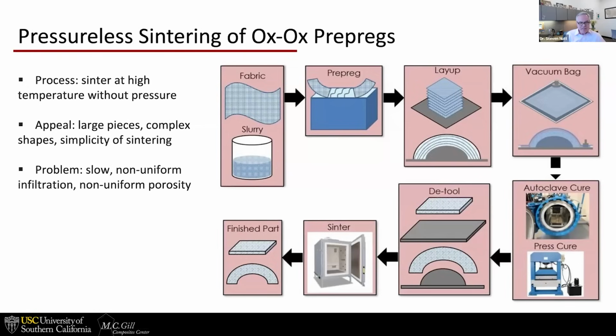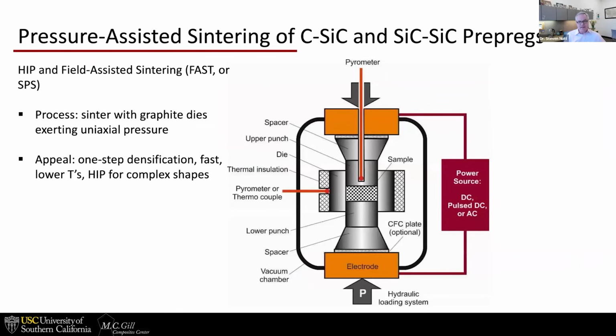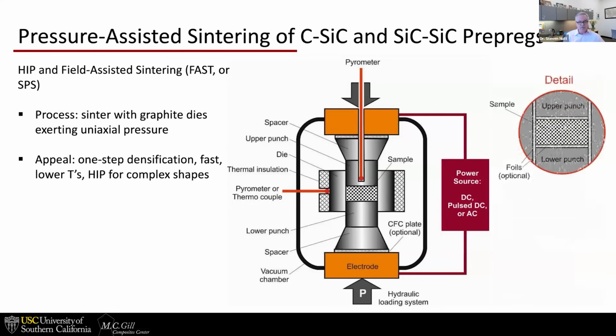There's the problems. It's a non-uniform infiltration of the ceramic slurry and non-uniform porosity. Okay, talk about that in a minute. A fourth process route is just pressure-assisted sintering. There's two variants. One is very well known, and that's hot isostatic pressing. The second one is maybe less well known, field-assisted sintering, or commonly known as spark plasma sintering, where an electric field is applied during sintering, either DC or AC, and that greatly accelerates the densification process down to like minutes. So that's a huge appeal right there.